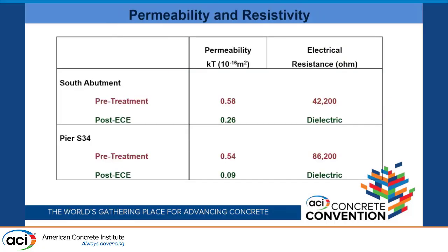And probably the most interesting part of the data, because it contradicted certain things that were seen in the research that was done in the lab, including the stuff at University of Waterloo, as well as in the SHARP program, was that some of that lab research had shown that permeability of the concrete increased as a result of chloride extraction, and also that the electrical resistivity of the concrete also in some cases increased as well. Yet the results from the field, actual field sites, were exactly the opposite.